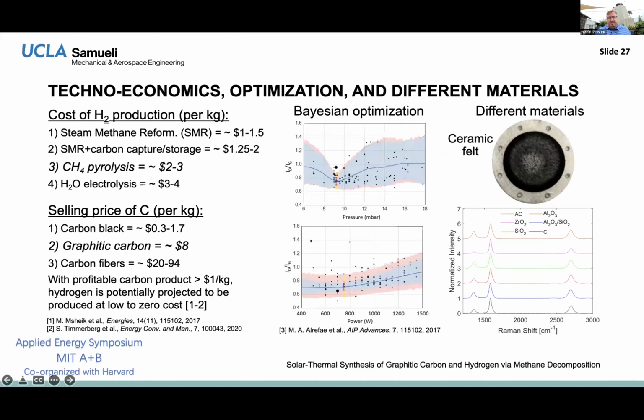Here's just an example of some things that we've done to start on the optimization question. This is a Bayesian approach that we used for making graphene, optimizing pressure and optimizing the power of the system, and we're applying these principles to that. We've also, and this gets back to the question of catalysis, grown this graphite on lots of different materials. The starting carbon felt, I mentioned, was PAN fibers. It's basically irrelevant. All you really need in this process, we found, is a felt or porous material that can withstand the temperatures of the process. So we put it on all these different oxides, and we get the same thing.